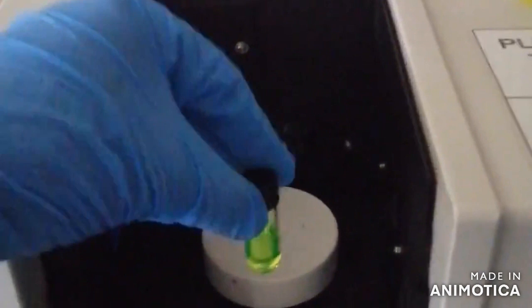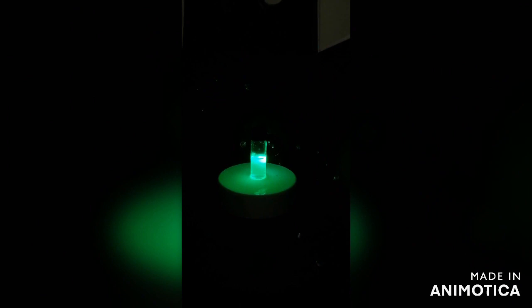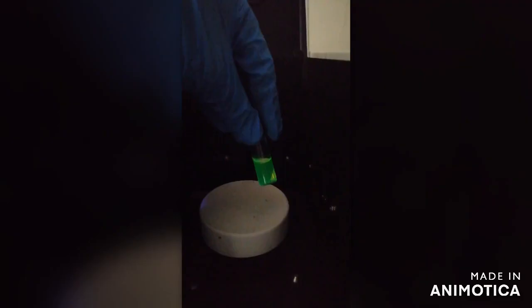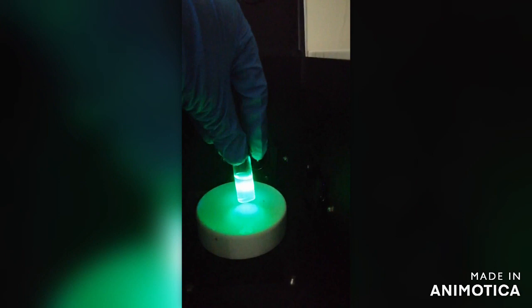After the washing of these nanoparticles, we can see they are extremely bright, with emission at 515 nanometers under the UV lamp. Moreover, the colloidal stability of this nanoparticle ink is extremely high, and they have very sharp emission.